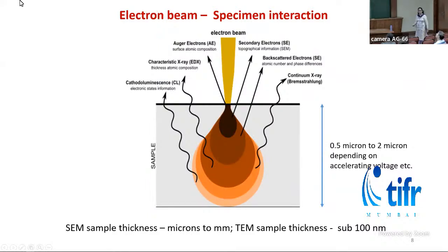Now, how is image formed using SEM? So when this electron beam falls on the sample, different kinds of signals are emitted from the sample, which are secondary electrons, backscattered electrons, characteristic X-rays. If we analyze these signals properly, then we can get a lot of information about the sample.